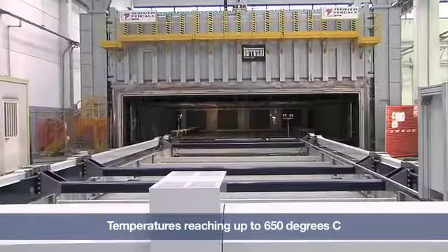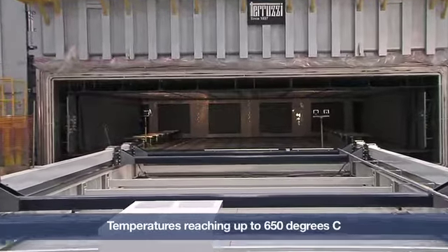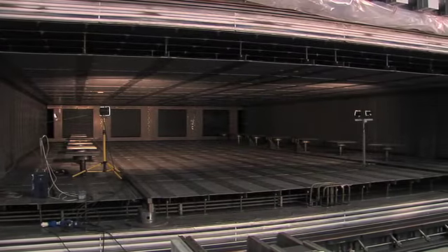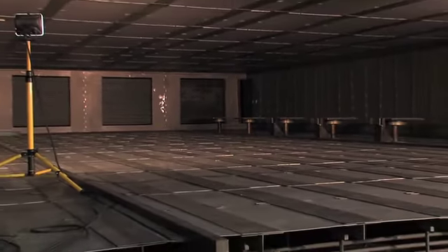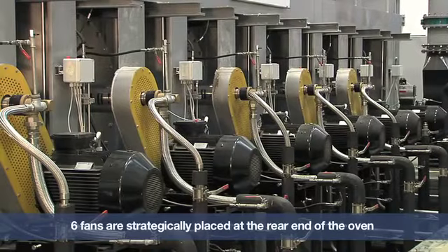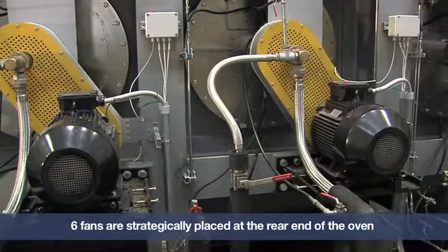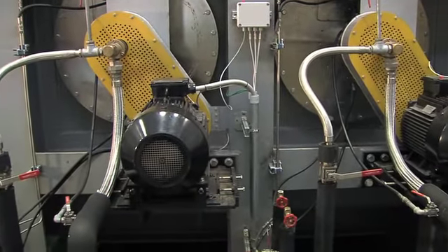The heat treatment is carried out at different steps and temperatures reaching up to 650 degrees Celsius. The temperature homogeneity required is plus minus 5 degrees Celsius and the heating rate 5 degrees Celsius per hour. The heat treatment is carried out in controlled inner atmosphere, with maximum level of oxygen impurity being at 200 parts per million. One of the main challenges is the homogeneity required, plus minus 5 degrees Celsius, on such a large component. 6 fans are strategically placed at the rear end of the oven to guarantee a homogeneous heat treatment.